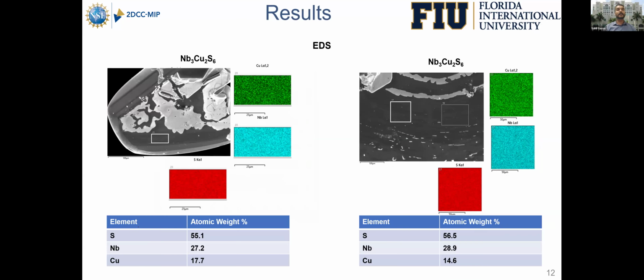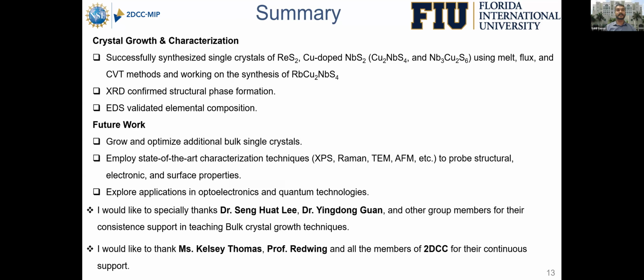Moving forward with niobium copper sulfide, we got the same results, where the copper, niobium, and sulfur are uniformly distributed all over the surface, and I have tested two different crystals, but I'm getting almost the same results. So based on this, I'm summarizing my results that we successfully synthesized single crystals of ReS2 and copper doped niobium sulfide using melt, flux, and CVT methods.